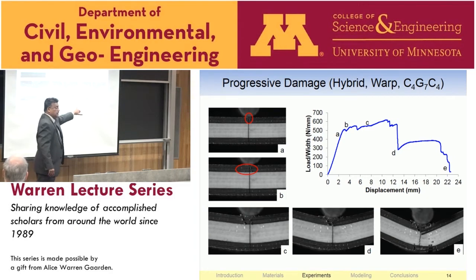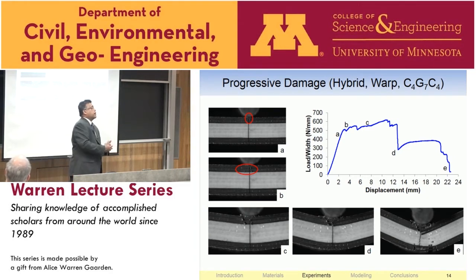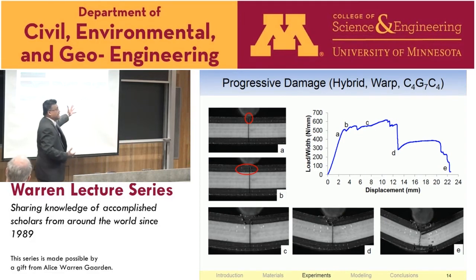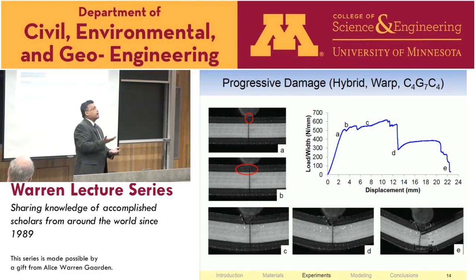Now, after point E, when you unload it, there's a lot of elastic spring back. Unlike a steel, if a steel structure is bent to this level, when you unload, it stays. You disrupted the geometry. Here, it's damaging. It's not permanent set, so it comes back. Now, it will not come back exactly because the path of reversibility is not exactly satisfied. So the crack opens up, and when it comes back, it doesn't come back exactly the same way. That's why there is a little bit of residual damage left in the structure.